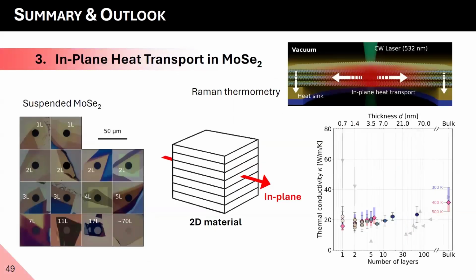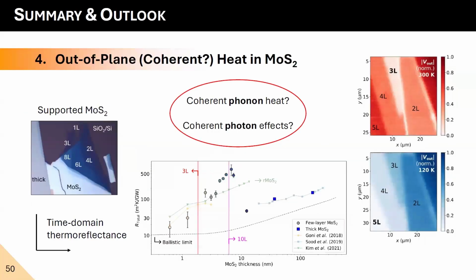In the third section, we've exploited our suspended molybdenum diselenide flakes for in-plane heat transport experiments, and we've seen how our results filled the gap in the literature. In the last part, we've used our supported molybdenum disulfide flakes. We've performed time-domain thermoreflectance and obtained the total thermal resistance for many flakes with many thicknesses, agreeing in the thin and in the thick part, and showing strange behaviors for intermediate flake thickness, which we tried to explain using coherent phonon heat and coherent photon effects.